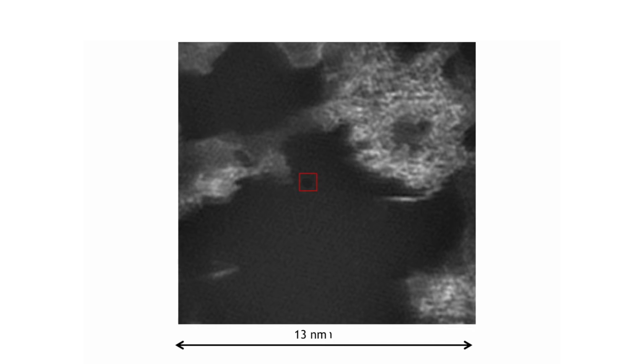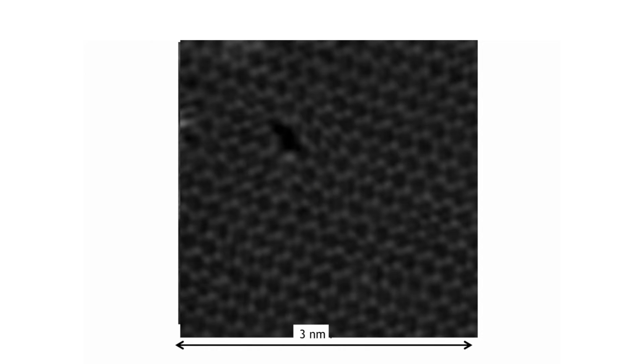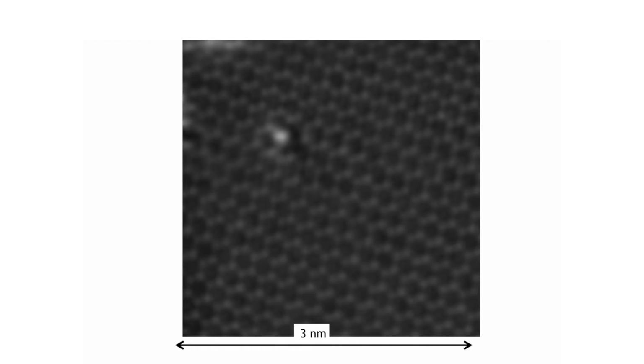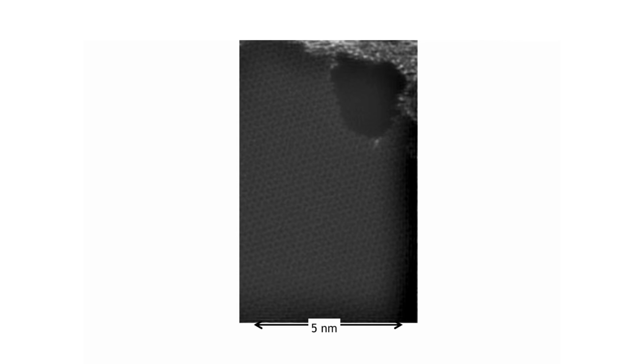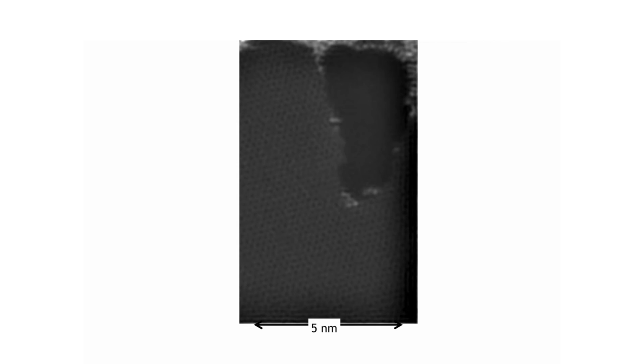We zoom into another area, so here we see a double vacancy. And then we carry on, and something has attached itself to the double vacancy, and it's a silicon atom. Now, this also happens with other atoms, in particular metals, and then something called metal-mediated etching, or etching catalyzed by the metals, occurs. The metal atoms, you can see them as the white little dots, zoom around the hole in graphene and enlarge it and enlarge it and enlarge it and make it bigger.